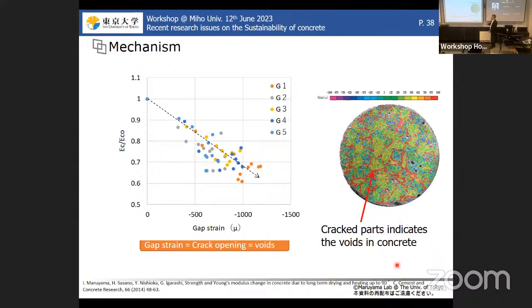So therefore, assuming that the crack opening can be evaluated by the difference between the strains of concrete and mortar at the same drying condition, if you plot the Young modulus reduction as a function of the gap strain, we see a relatively nice correlation. So we found that the Young modulus is deteriorated by the crack opening inside of concrete.